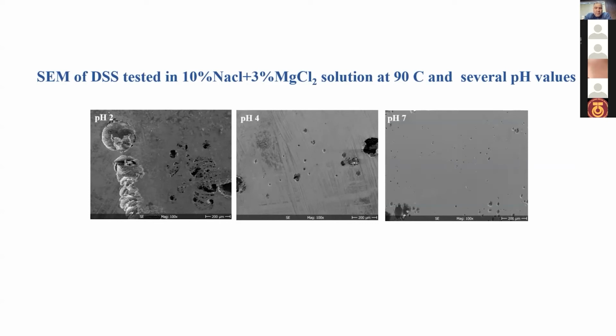SEM observation supports the results obtained in the electrochemical test, and we show that the surface at the pH 2 is entirely pitted, and there is a significant increase in the size of pitting and the number of pits when decreasing the pH. We note that the pitting corrosion was very small and very little at pH 7, and it increased gradually with the pH decrease to 4, and became very big and very large when the pH decreased to 2.